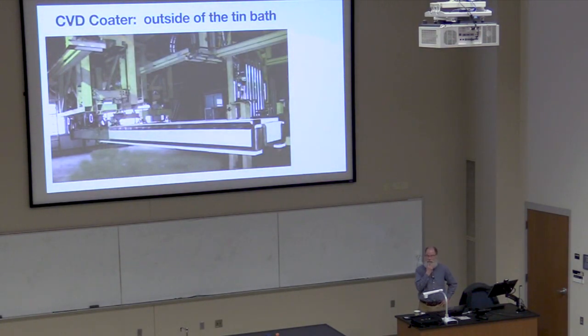So this is an example of a CVD coater, and this is outside the bath, meaning this is on the plant floor after it's been cleaned. When you're ready to coat, you roll this in, this is a trolley system up here, you roll that in and stick it into the bath and lower it down on the glass. So it's hard to see much here because, so this is a beam, that's just a beam to support the coater. There's a beam on the other side. Then there's insulation, because if you put metal beams in that hot bath, they're going to sag, right?